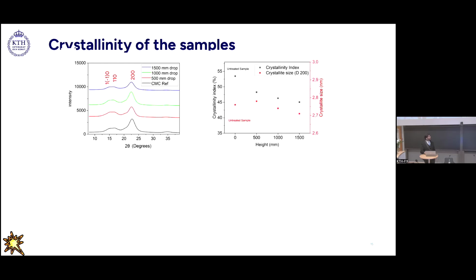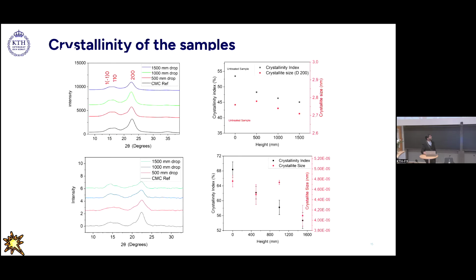Just from the observation point of view, you can see that the crystallinity index was showing a decreasing trend. As we increase the intensity of the shock wave, the crystallinity of cellulose was going down. Also, the crystallite size for the 200 peak, the major crystalline peak of cellulose, was going down, which is very intuitive considering the crystallinity is going down as well. And the same phenomenon was also repeated in the WAXS measurement, which was done on the wet samples. So we have a decreasing trend in the crystallinity as well as the crystallite size.